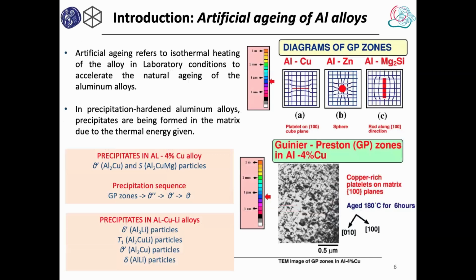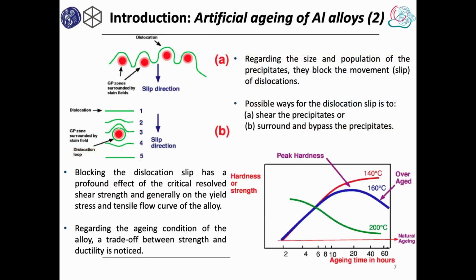And some background for aluminium alloys. Aluminium alloys are precipitation hardened alloys, and we can increase or adjust the properties by an appropriate heat treatment, and precipitates can influence the dislocation movements, and therefore we can have adjusted stress-strain behavior of the material. For precipitation hardened alloys, we need to optimize the heat treatment. We have a competing situation between temperature and time. In the first stage, we have improvement of mechanical properties up to the peak aging condition, and afterwards we have a decrease. So we have to find a good balance for the heat treatment.